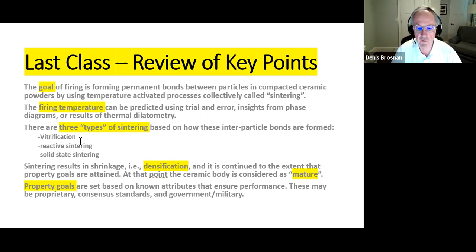Now, the consequence of sintering is shrinkage. We have the same weight, but the ceramic shrinks. We have firing shrinkage, and that means that the density increases. So sintering achieves densification. And of course, we usually see that most of the properties of the ceramic improve dramatically at some stage in densification. And we say that the ceramic is fully mature when it's achieved an extent of firing that gives us the properties that we want in firing.